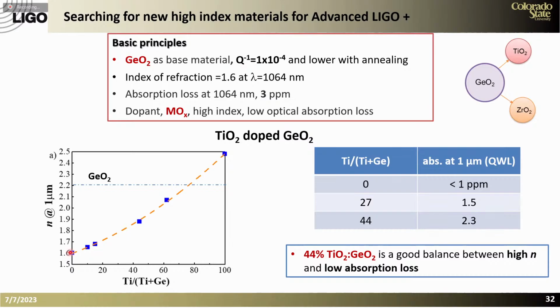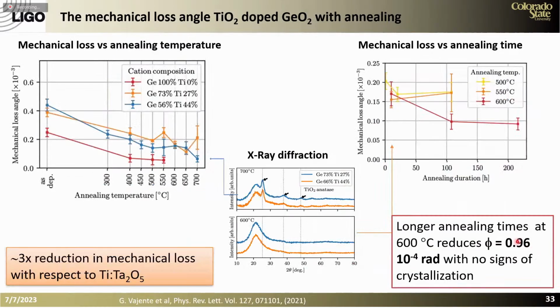So there isn't that large of a contrast. But by adding titania, we can actually increase the refractive index. And we demonstrated that we can make films with a very low absorption loss as well. We carried out extensive studies of the mechanical loss and actually showed that when we have approximately 44% titania into Germania, and we anneal the sample, we can actually get a very low mechanical loss.